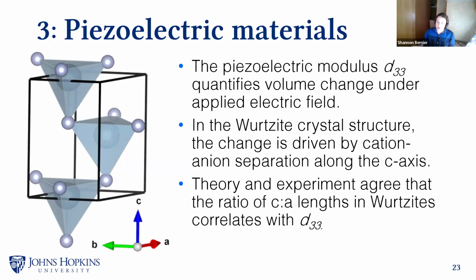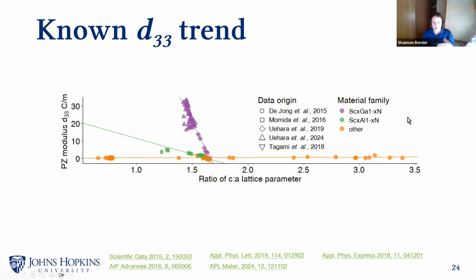One of the most well-studied families of piezoelectrics crystallizes in the Wurtzite crystal structure, which is hexagonal. When you're just looking at a singular parallelepiped, the actual hexagonal structure will have some rotational symmetry that looks more like the real material. In the Wurtzite families, the volume change of a piezoelectric is driven by cation and anion separation that lies along the C-axis, which is the long axis here. And I'll remind you that in a hexagonal crystal structure, the A and B are the same. Theory and experimental results on Wurtzite specifically have found that if you plot the C to A ratio, you can end up with a correlation with the D33 value. And that's what this plot shows you.